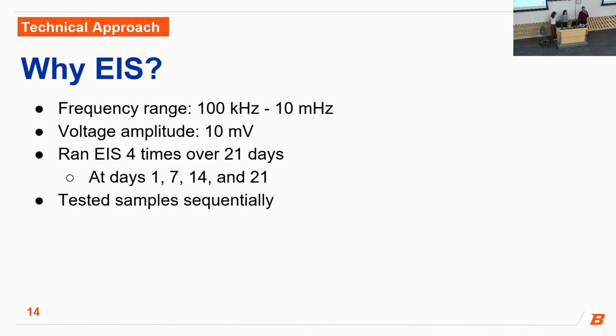EIS was used to characterize corrosion because it is non-destructive, evaluates coating degradation, and helps to understand the mechanisms behind passivation. Some of the parameters used for EIS include frequency range and voltage amplitude. A frequency range of 100 kilohertz to 10 millihertz was used to capture the full electrochemical spectrum, ranging from high frequency ohmic resistance to low frequency charge transfer reactions necessary to calculate corrosion rates. We applied a 10 millivolt amplitude to ensure a linear response from the system while providing a high enough signal to noise ratio for accurate data collection. Due to the setup being limited to testing one sample at a time, the samples were tested sequentially.